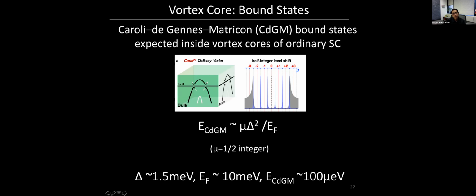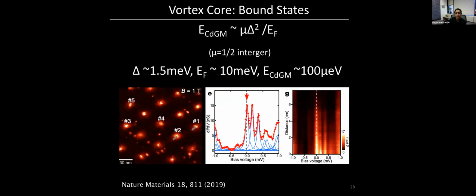Now, if you think about the surface state that we see in FeSeTe, the Fermi energy is less than 10 milli-electron volts, and the superconducting gap is around 1.5 meV. And if you plug these numbers in, you realize that the trivial bound states should have energy scales of about 100 micro-electron volts, which is actually pretty large for STM at low temperatures.